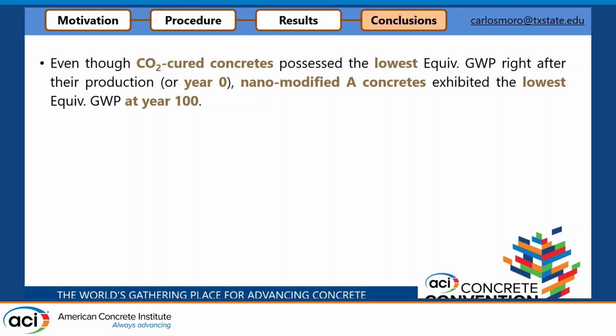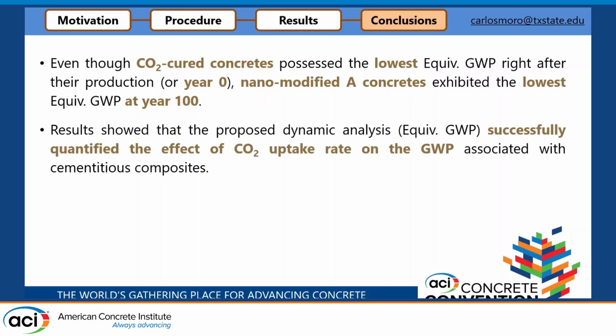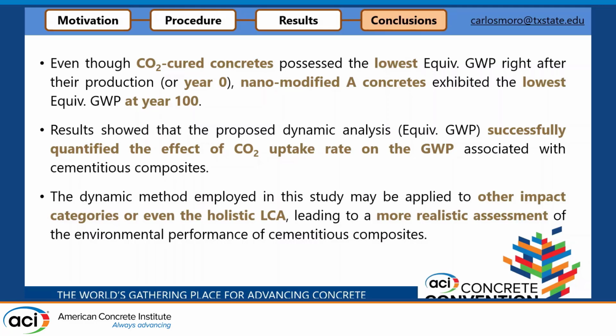Okay? So the conclusions here are that even though CO2 cured concrete possesses lower equivalent or dynamic global warming potential right after the production, the nano-modified A concrete, which is the one that accelerates all the time, exhibited the lowest at year 100. The results show that this proposed dynamic analysis successfully quantified the effect of CO2 uptake rate, because the final value is not the same for all the concretes, and that this dynamic method is only a first step.